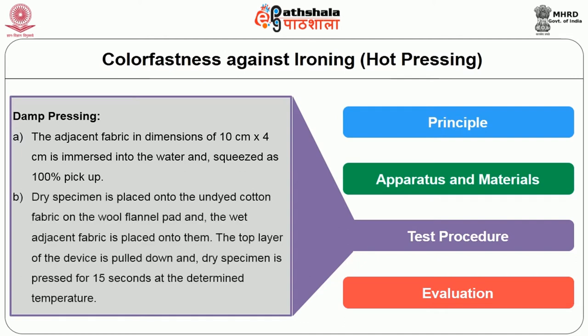Dry specimen is placed onto the undyed cotton fabric on the wool flannel pad, and the prepared wet adjacent fabric is placed onto them. The top layer of the device is pulled down and the dry specimen is pressed for 15 seconds at the determined temperature. The color change of the specimen is then noted down.